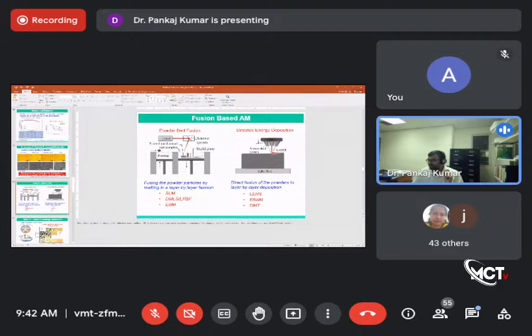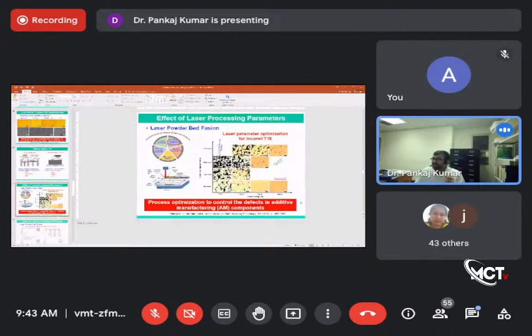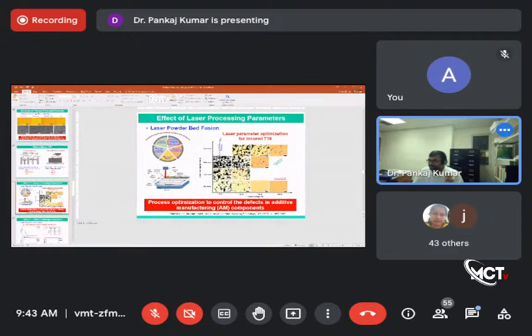Okay, so for the fusion based technique, we already talked about the powder bed, and then there is another technique, directed energy deposition, right, where we have everything here. Both start with the powder, and the idea is very similar. Only the process itself is a little different. Okay, so let's talk about the processing conditions, how the laser parameters change the performance. You have different parameters that you can control. You can control the laser beam diameter, the hatch distance, the layer thickness.